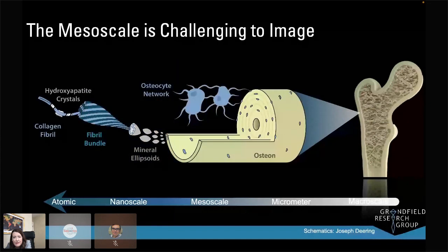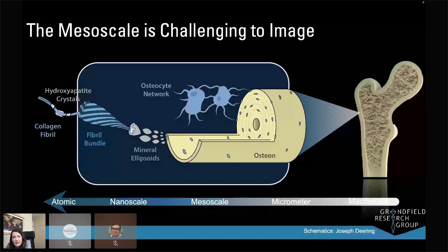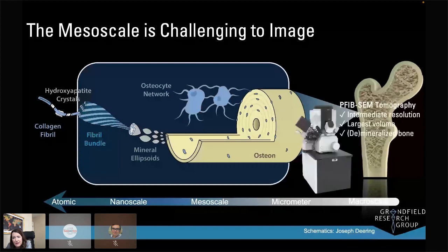But if we want to probe the mesoscale, this really means covering the microscale volume all the way to the nanoscale. This would encompass things like full cell networks and other details that are hard to view when looking at such small regions as were shown previously. So to access this, we're using a plasma FIB, which gives us quite good resolution, the largest volume we can achieve with high resolution in an electron microscope, and allows us to look at different types of bone.